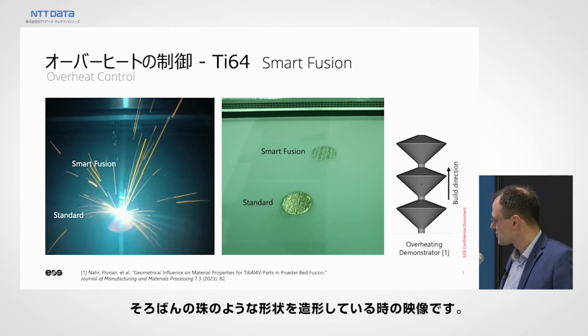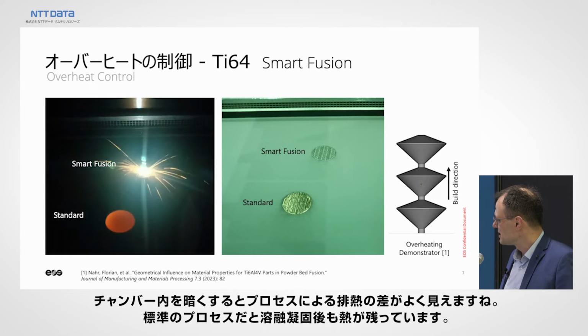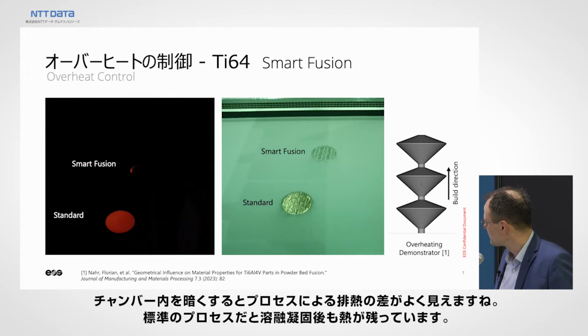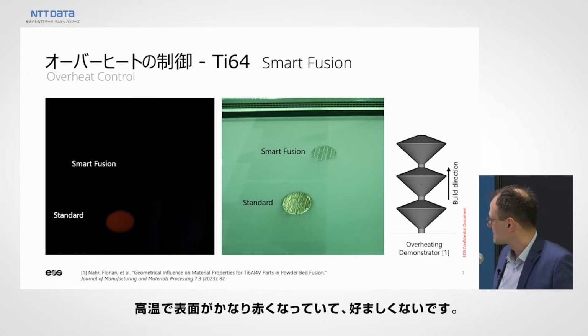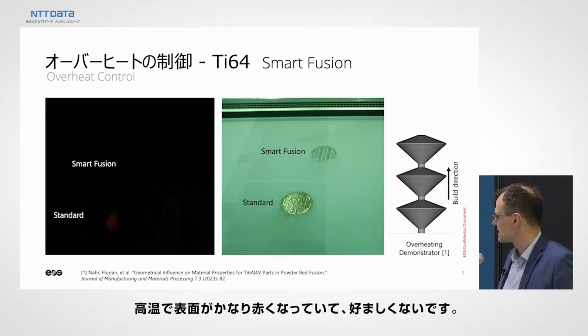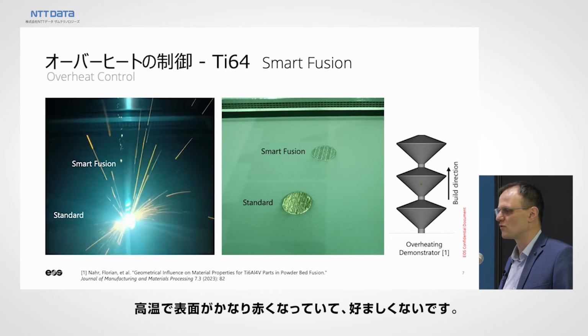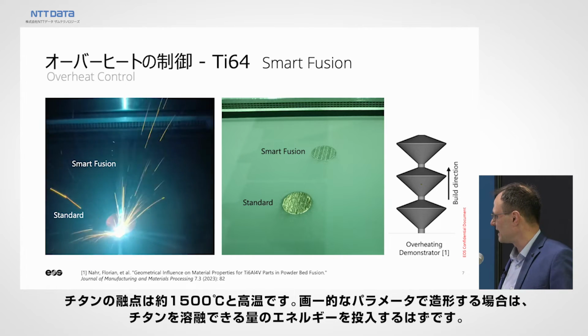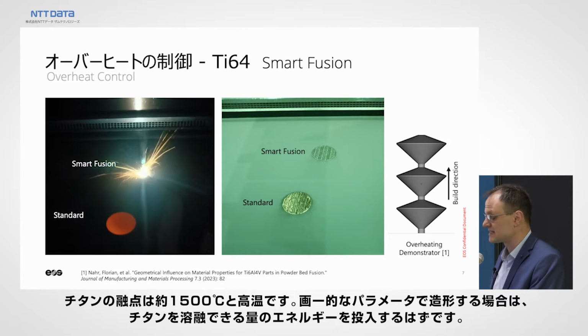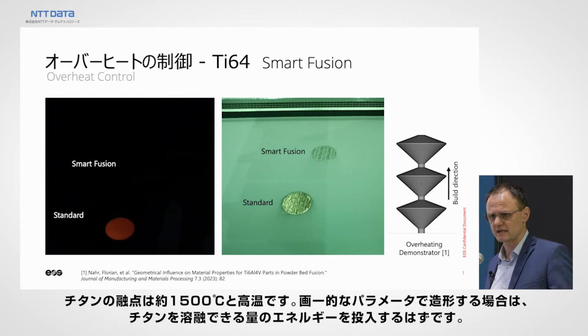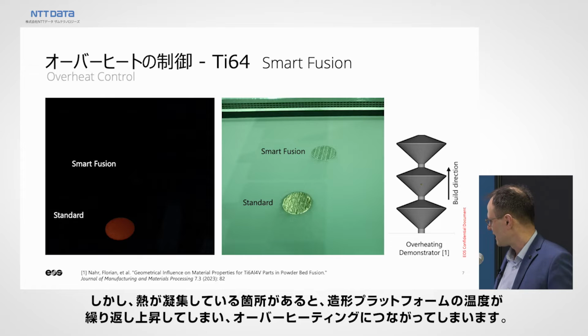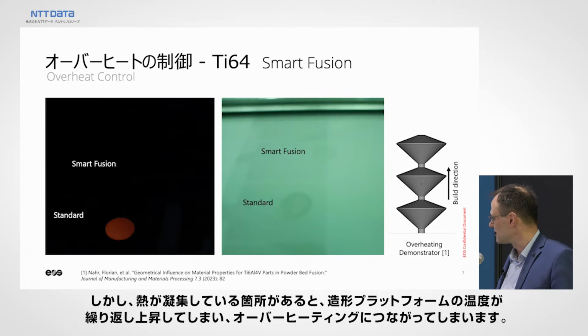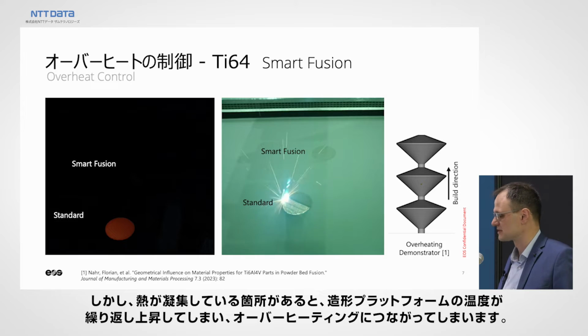Yes, so with the standard processing, if you switch off the process chamber light, what you really see is this afterglow of your part. If you print, for instance, this pyramid, so we are about this height, and this is really glowing, hot surface, and that is not good. That is something that you typically don't want to see in your processes, and the reason is that it is a titanium process. An example: titanium melts at 1,500 degrees centigrade approximately, and with the laser, with a fixed process parameter, you're adding exactly the right amount of energy to melt the material. But if you have a funnel there where the heat is agglomerating, your building platform temperature is rising over and over again, and you're leading to overheating. So this is a bad effect.